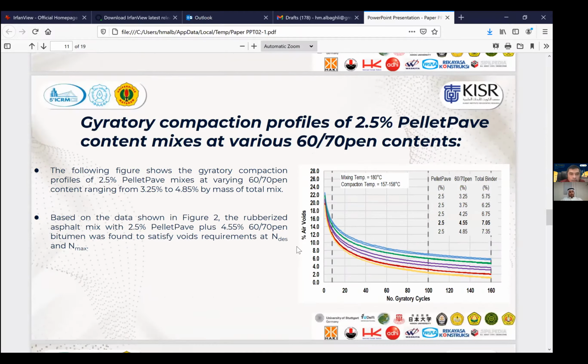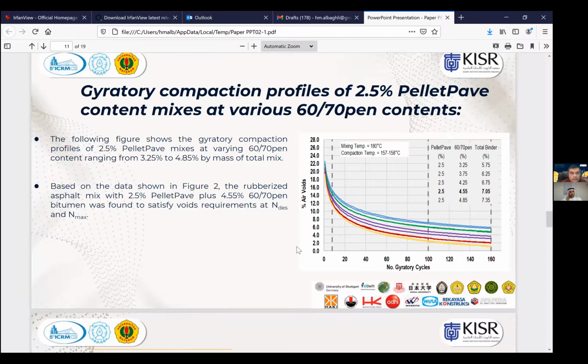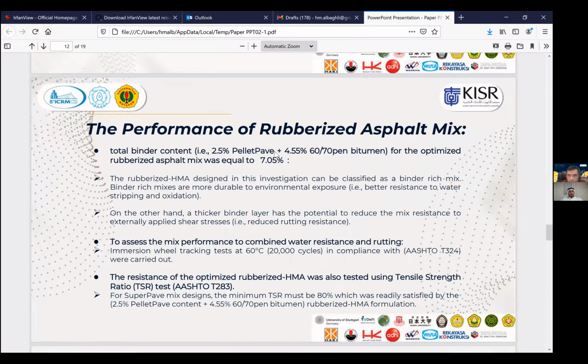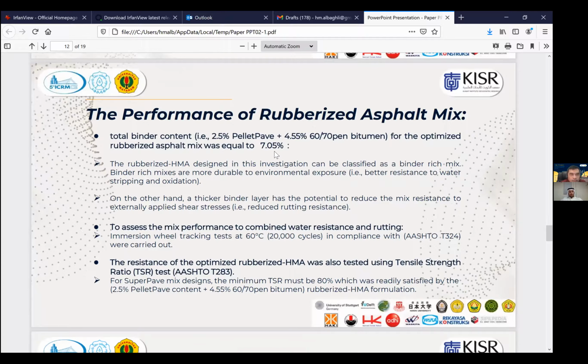The newly introduced Pellet Pave content was 2.5% at varying bitumen content ranging from 3.25 to 4.85 by mass of total mix. Finally, the 2.5% Pellet Pave content plus 4.55 bitumen satisfied the void requirement. The overall binder content was 7.05, which in this case is considered a binder-rich mix compared to typical non-rubber modified mixes.